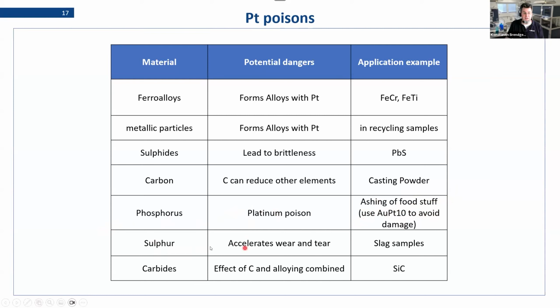Sulfur in general has the same effect as phosphorus. Basically, it has effects on the surface and it increases the aging. We find this a lot in slag samples. So be careful with sulfur and sulfide samples. SO3 sulfates are usually not a problem. So yeah, you want to be oxidizing before.